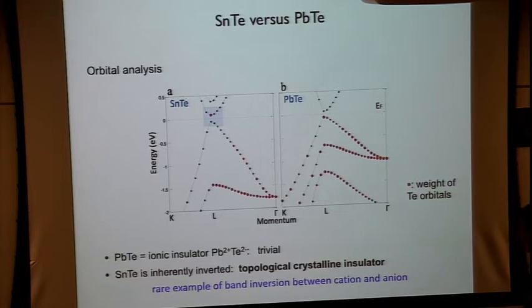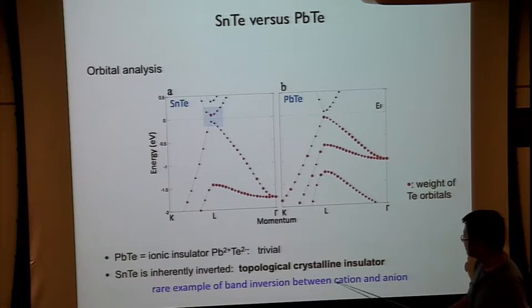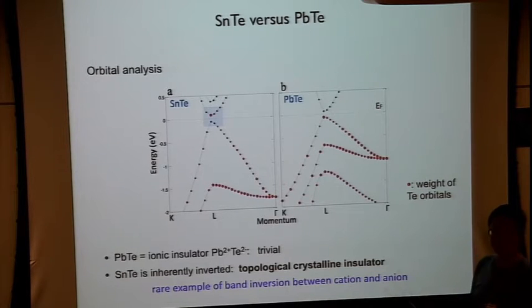All right. So in this particular example, as is shown here, band inversion occurs between the cation and anion, which is actually a very special, unusual case. For example, in other topological insulators like bismuth telluride, bismuth antimony, and many others, band inversion occurs between the s and p orbitals of the same atom. For example, in mercury telluride, band inversion occurs between the s and p orbitals of mercury, or between the covalent bonding and anti-bonding orbitals. And this is a rare example where band inversion is between cation and anion. So I think this is related to some of the interesting chemistry in these materials.